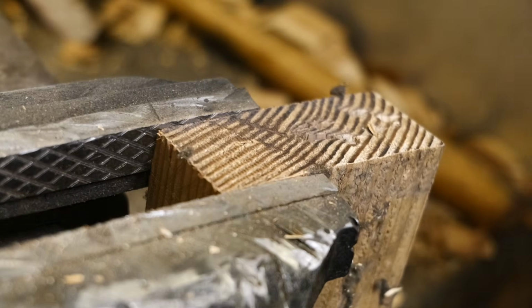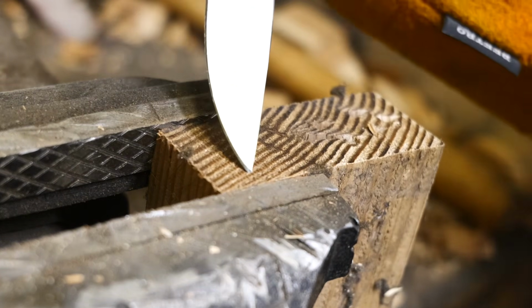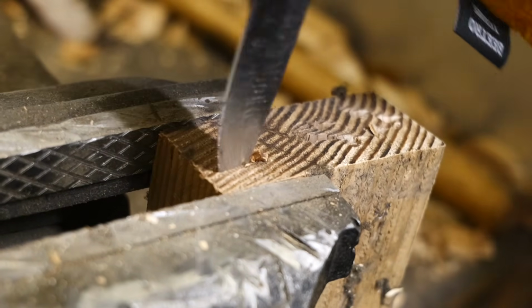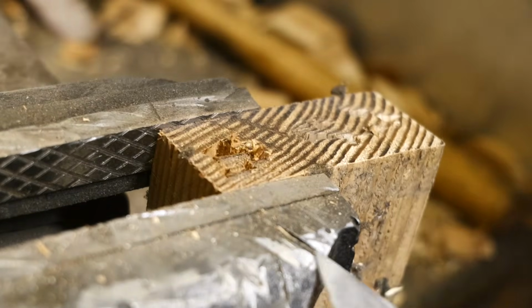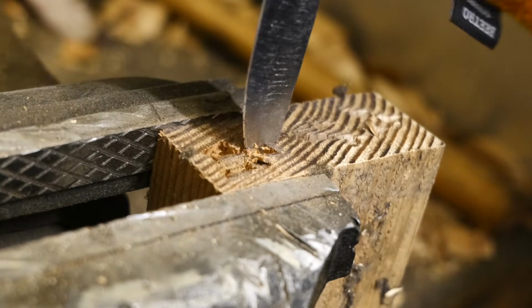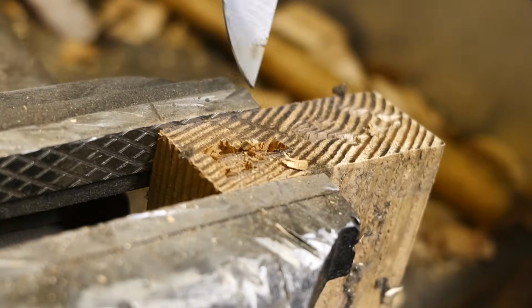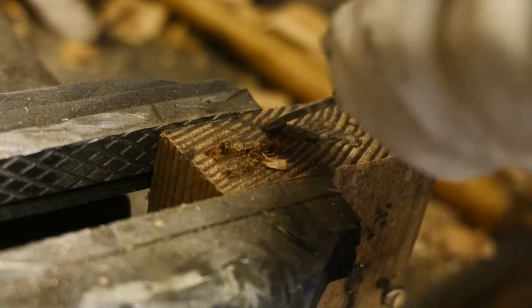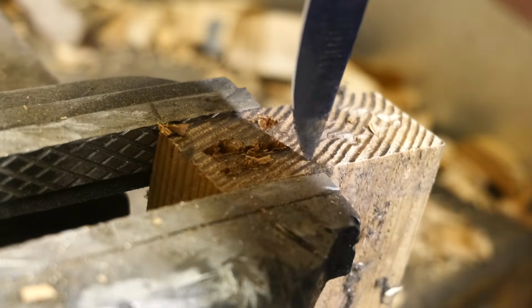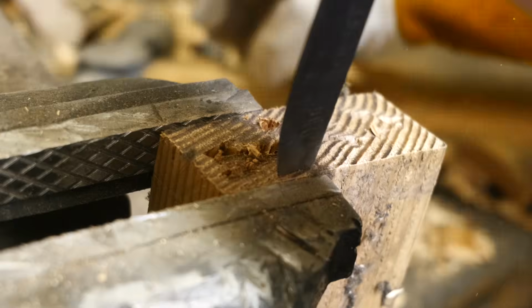I put the tip into this 2x4 and pried it out. Now, the first 5 times by stabbing it in, it did great. When I hammer it in and pry it against the edge of the vise here, it does snap, which really is not a surprise, especially at this HRC. Maybe I shouldn't have done that last bit.